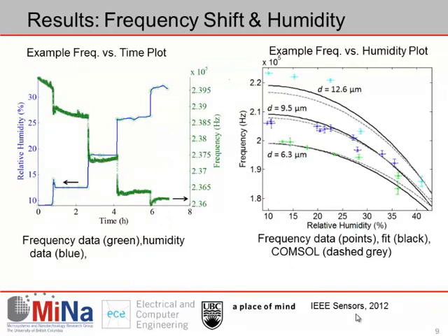The plot on the left, this one right here, describes frequency shift and humidity as a function of time. So the blue curve corresponds to humidity, ranging from 10 to 30% RH. So this isn't a full sweep. We're just looking at a small region here. And then the green points correspond to the resonant frequency shift of the device. A few things to take away here.